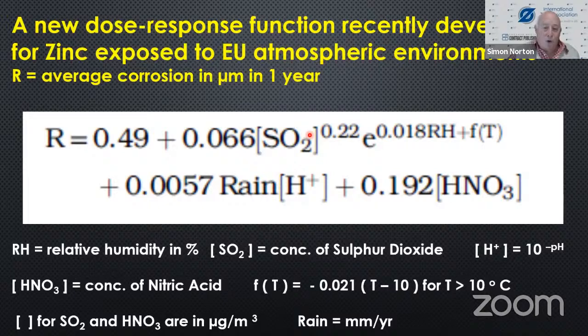However, if you have chloride corrosion, it increases as temperature goes up, and it's not in the dry deposition part of the equation. The last part here relates to rainfall and the pH of the rain and the role of nitric acid, which is now being recognized as having an impact on zinc. But be careful, this equation only applies to work done in the European Union, in European countries. Other areas might differ and other models might apply. But I thought I would show you how there's such a complex interaction of physical factors in corrosion of zinc.